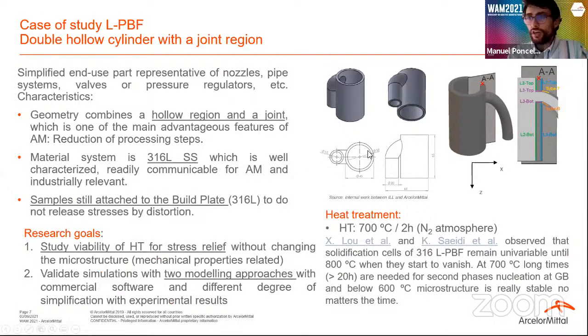We have been working with ArcelorMittal in a very fruitful collaboration. We like this geometry that we proposed, because it's a simplified geometry, but already representative of many final components like nozzles, pipes, valves, pressure systems, and so on. So we study the cross section of the sample here between the both cylinders, because this geometry combines a joint region with a hollow part, which is also one of the main advantages of additive manufacturing, to reduce the number of processing steps. So you build this sample at once, and you don't have to drill it or then weld it and so on.